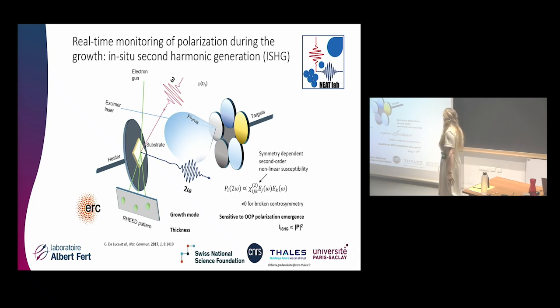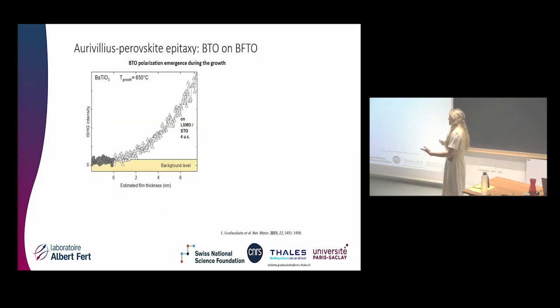So this is a typical growth of BTO. Here we have just a standard LSMO buffered STO, so a very normal growth done in our lab for many years. So you see that it takes, so this is the beginning of the growth, and then the thickness is increasing, and we're following the signal. You see that it takes around 2 nanometers, maybe a bit less, for the signal to come up, suggesting that this is the dead layer, right?